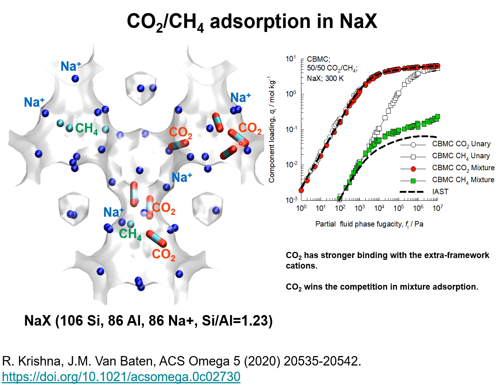The CO2 molecule experiences strong electrostatic interactions with the extra framework cations, and they congregate around the sodium cations, leading to an inhomogeneous distribution of the guest molecules CO2, methane within the pore space.